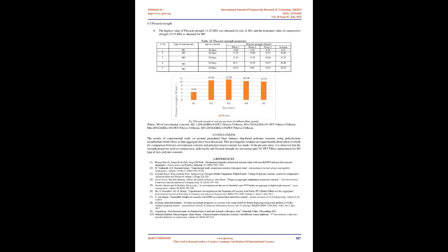5. Conclusions. The results of the experimental study on ground granulated blast furnace slag-based polymer concrete using polyethylene terephthalate bottle fibers as fine aggregate have been discussed. This investigation contains an experimental observation in which a comparison between conventional concrete and polymer-based concrete has been made. In the present study, it is observed that the strength properties such as compressive, split tensile and flexural strength increase up to 5% PET fiber replacement for the M3 type of mixed polymer concrete.